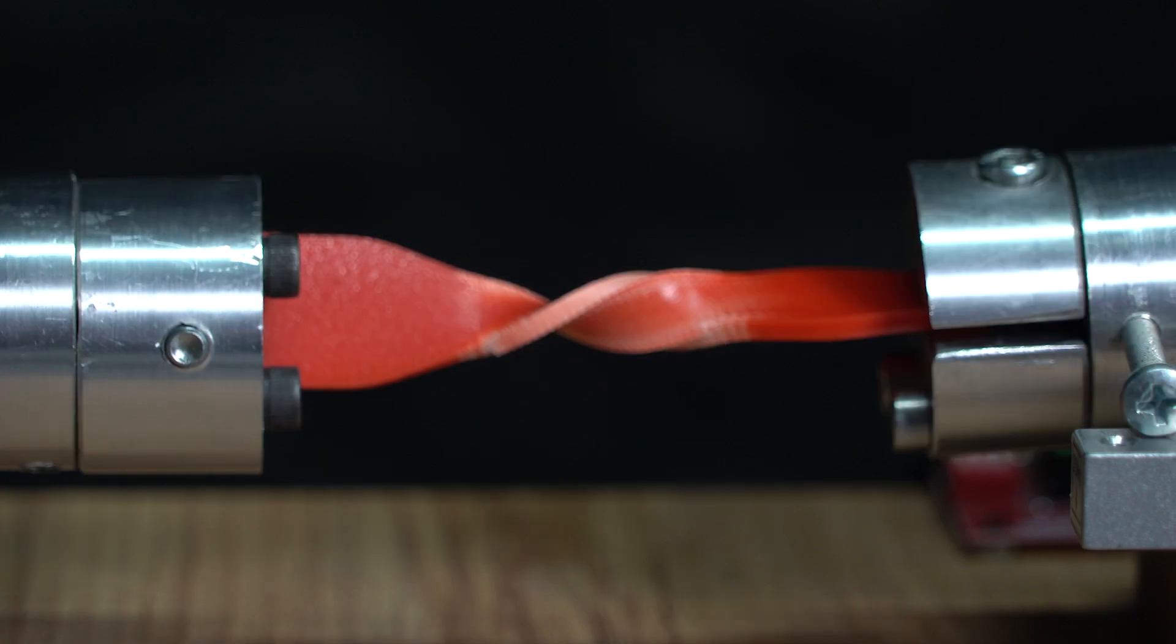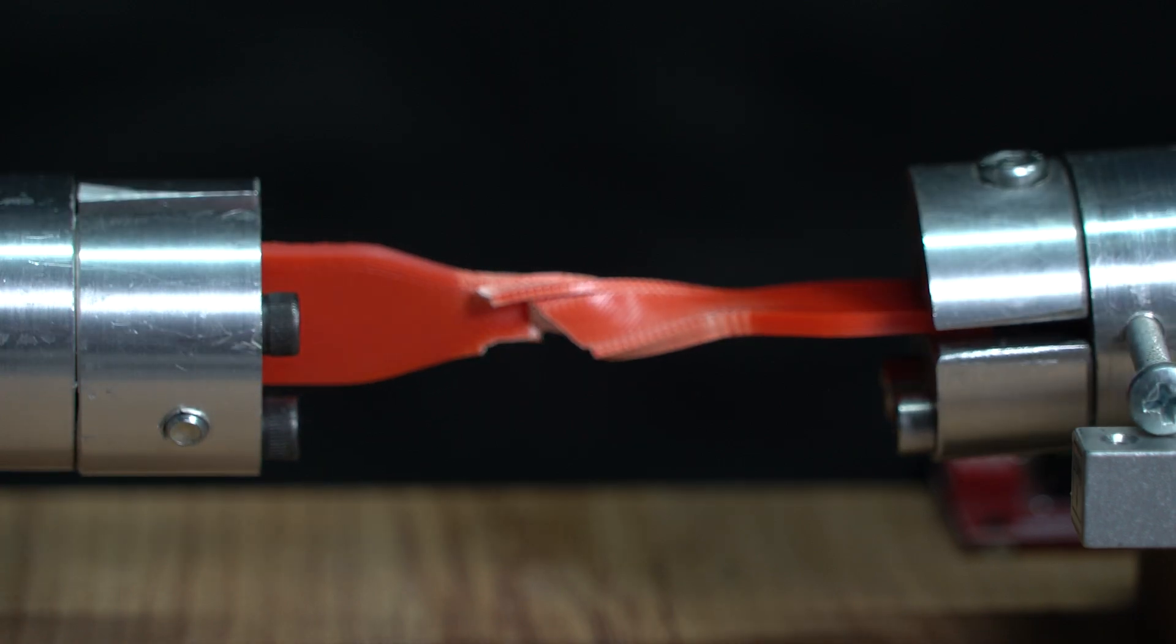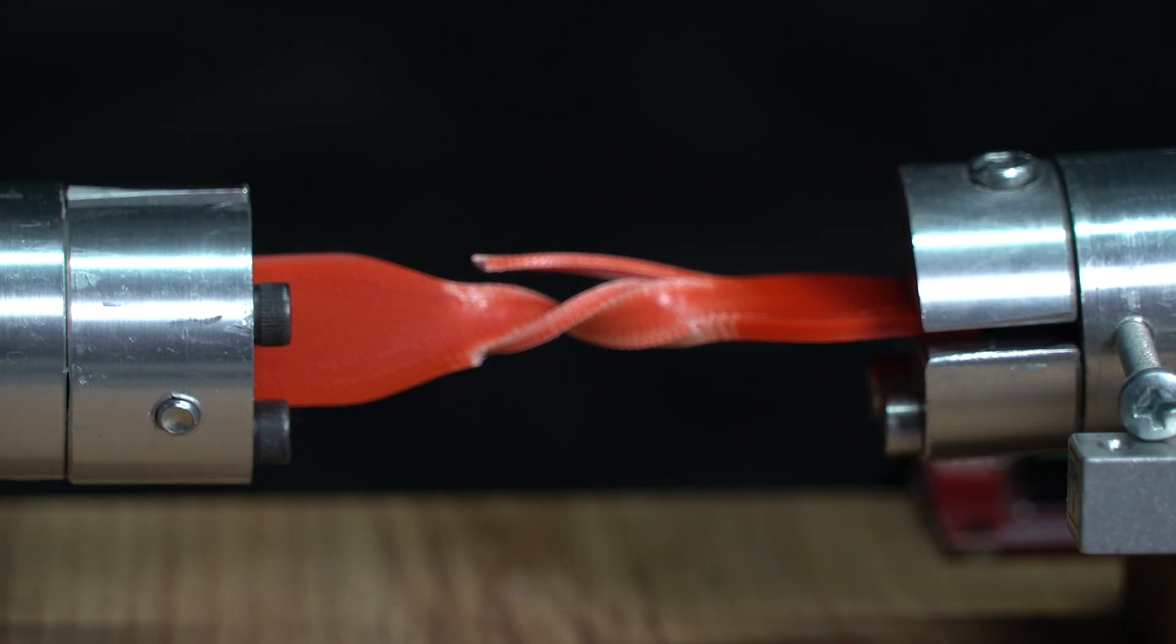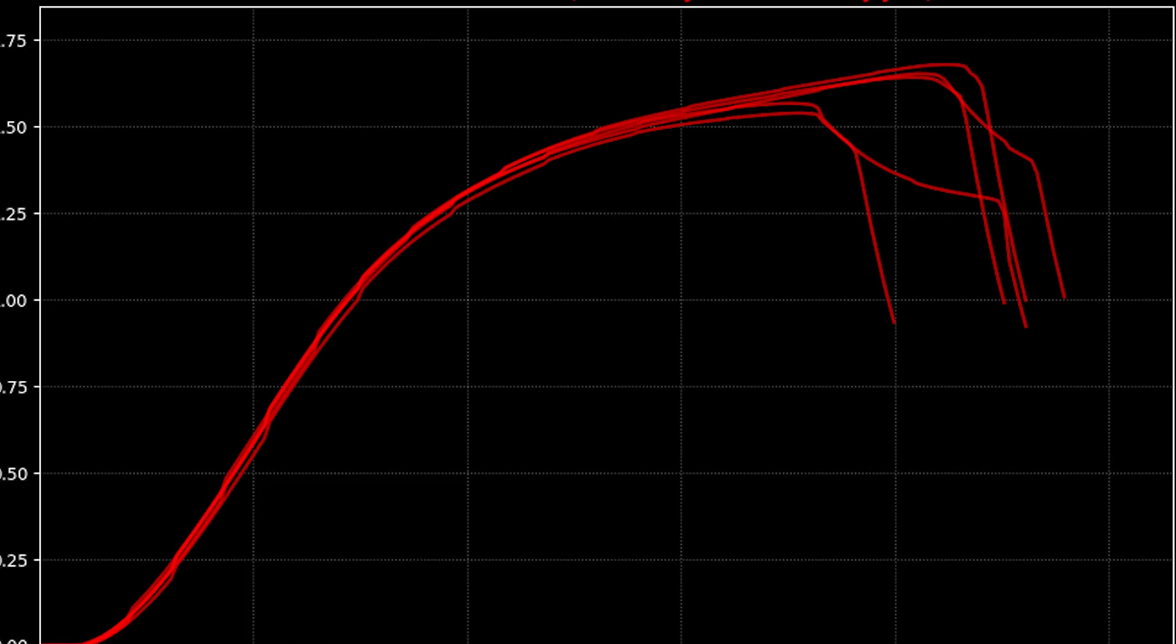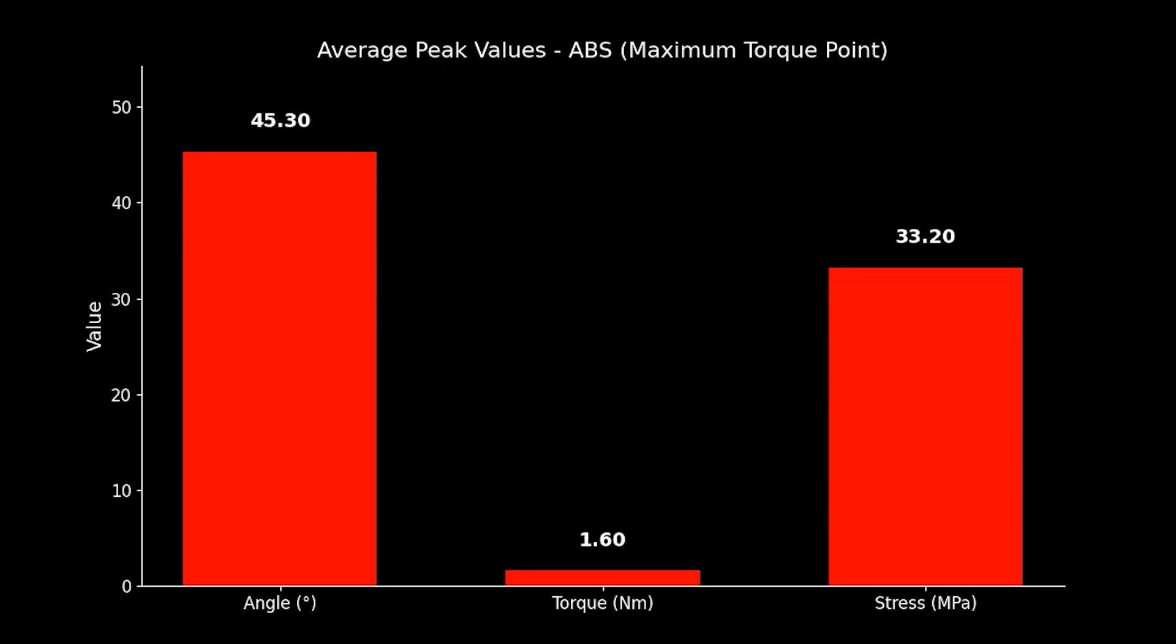We expect toughness from the tank. The results are in. Average torsion angle, 45.3 degrees. Max stress, 33.2 megapascals. Max torque, 1.6 newton meters.